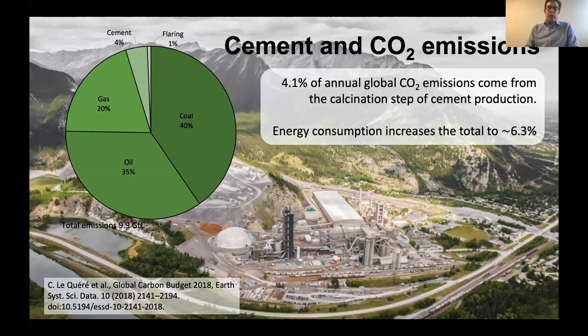A carbon budget that's published every year pegs that at about 4%, and that's only the direct emissions from the cement production. So the calcination reaction, where you turn calcium carbonate into reactive cement, calcareous cement phases, releases the CO2 that's bound in the limestone. If you then further look at the cement production as taking energy required to heat up the limestone for calcination, you'll have another 40 to 60% emissions on top of what the calcination provides. So if you looked at the total emissions for cement production, the most accurate carbon budgets are coming in around 6 to 7% of CO2 emissions associated with cement production and thereby concrete use.